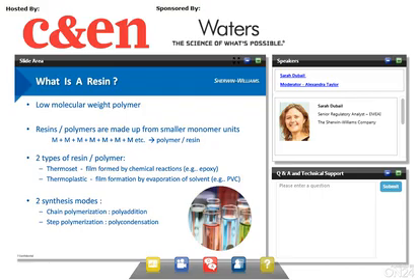They are formed by chemical reaction. Their molecular weight will usually be pretty low, between 1,500 and 10,000 daltons, and their property is to become permanently hard and rigid when heated. The thermoplastic resins are capable of film formation by evaporation of solvents. For example, PVC, the molecular weight is a lot higher, can be up to 250,000 daltons, even more, and they are substances that become soft and pliable when heated, or they can stay adhesive. And the synthesis mode of resin can be of two kinds, either polyaddition without any loss during polymerization, or polycondensation, which consists in a chemical reaction with some loss like water.